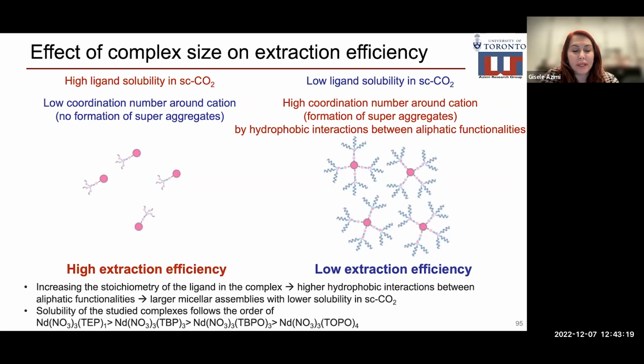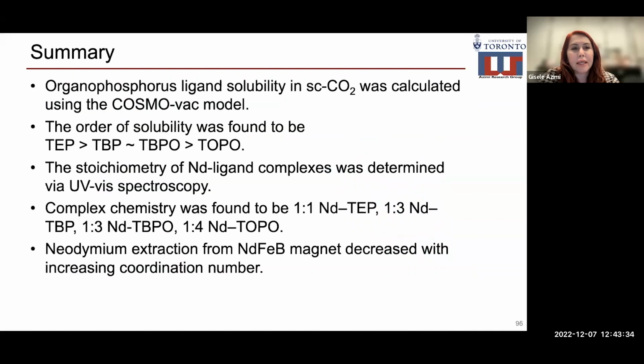Neodymium nitrate 3 TEP1 is higher than neodymium nitrate 3 TBP3, higher than neodymium nitrate 3 TBPO3, higher than neodymium nitrate 3 TOPO4. In summary, organophosphorus ligand solubility in supercritical CO2 was calculated using the COSMOVAC model. The order of solubility was found to be TEP more than TBP, equivalent to TBPO, higher than TOPO.